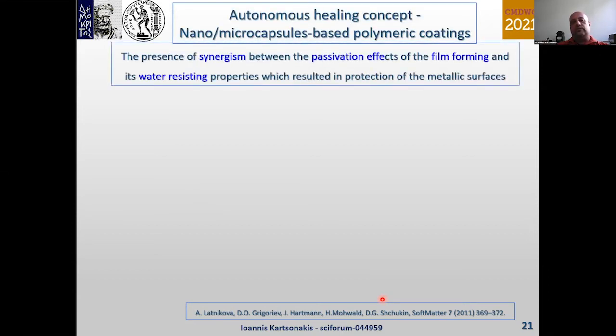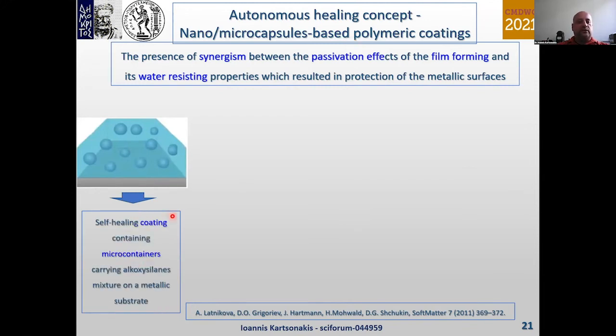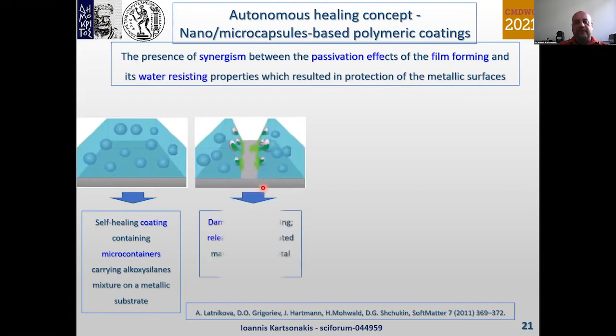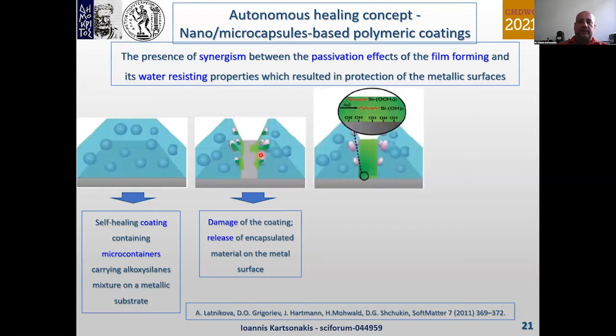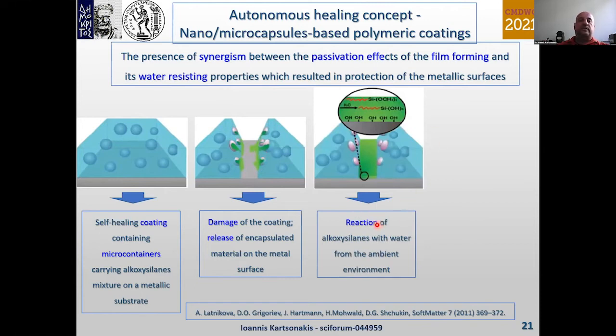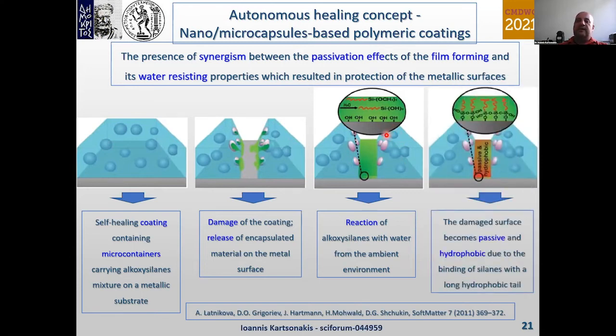Regarding the work of Latnikova in 2011, also with autonomous self-healing coatings, there was synergism between the passivation effects of the film forming and its water-resisting properties, resulting in the protection of the metallic surface. We can see here the coating containing microcontainers loaded with alkoxysilane precursors. After the crack formation, there is a release of the metal-organic compounds. Then there is a reaction of the metal-organic compounds with the water that comes from the environment. And finally, the damaged surface becomes passive and hydrophobic due to the binding of silanes with a long hydrophobic tail.